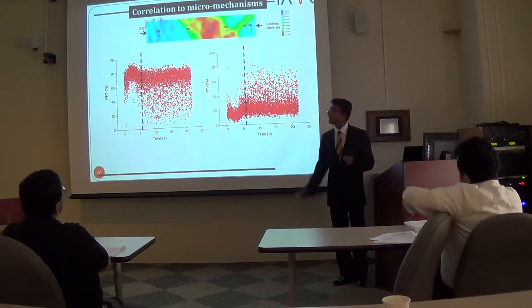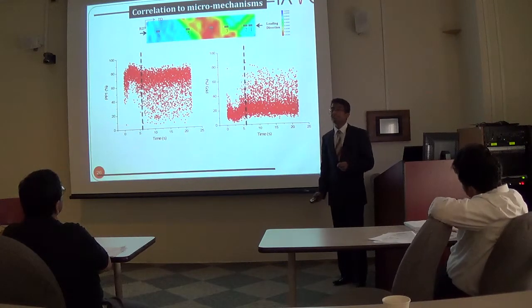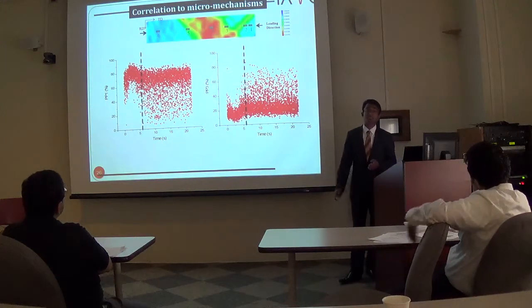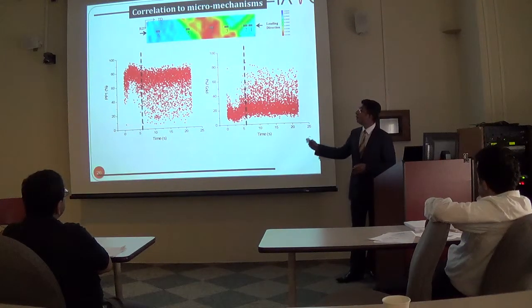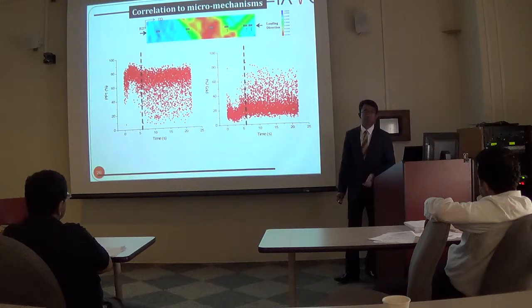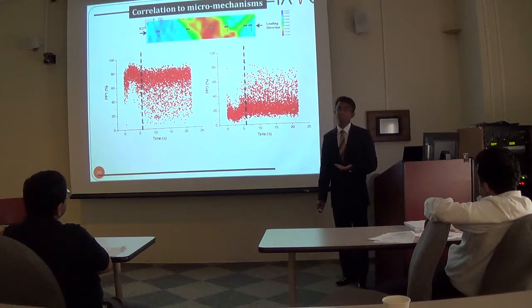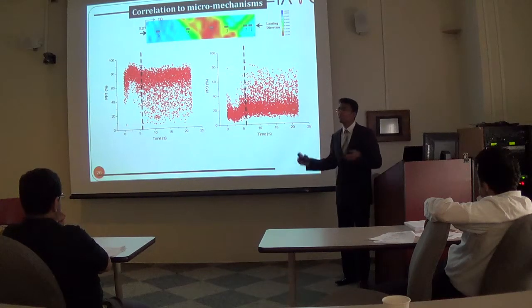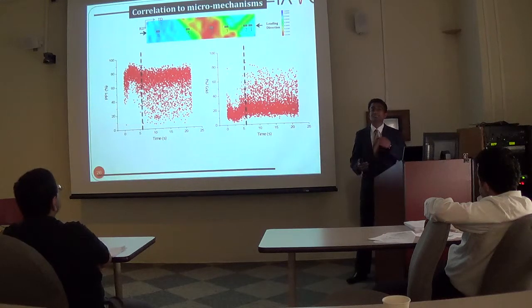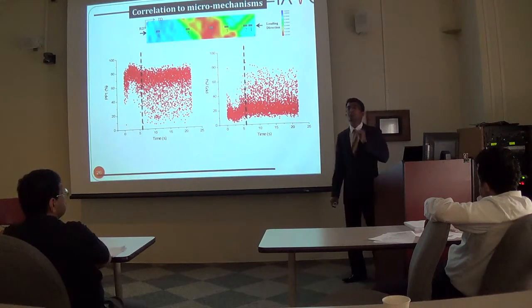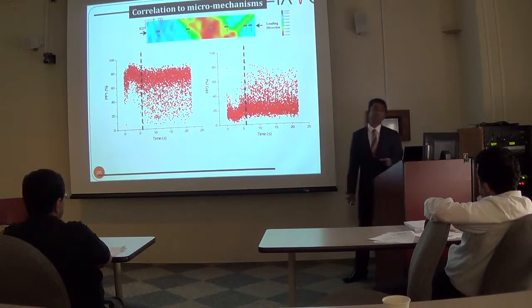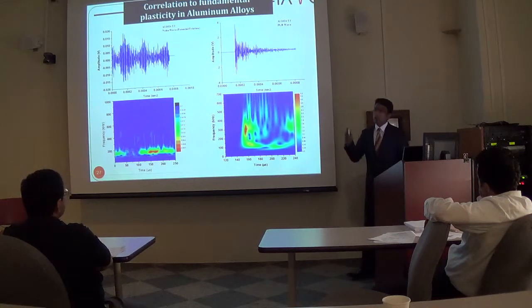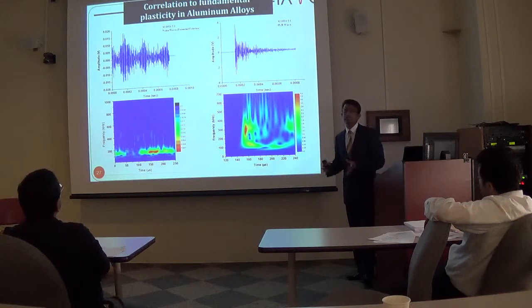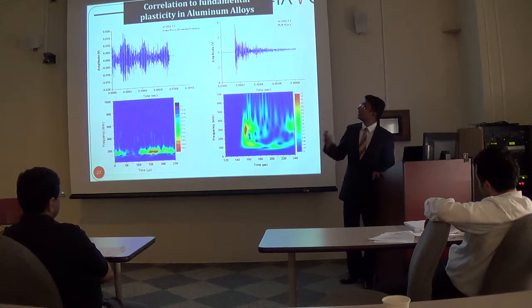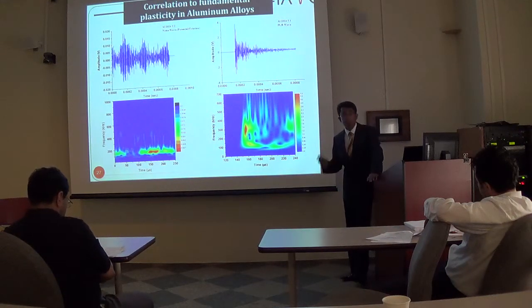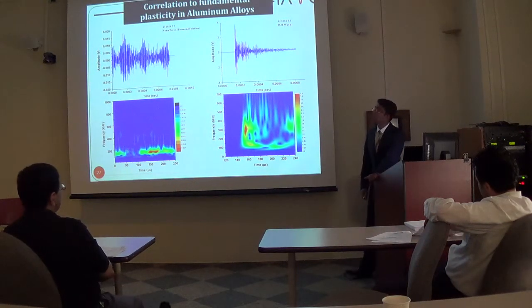What this means is that the low frequency signals are seen to decrease after the activation of the twinning mechanism of this material, while high frequency signals are seen to activate and dominate after the twinning mechanism. Thus, we can see how this sort of analysis can track in real time the actual evolution of the micromechanisms in the material. Now, the whole goal, though, was to see if this analysis can be utilized for detecting crack initiation and growth in the aluminum alloys, as was the objective with the ONR work.